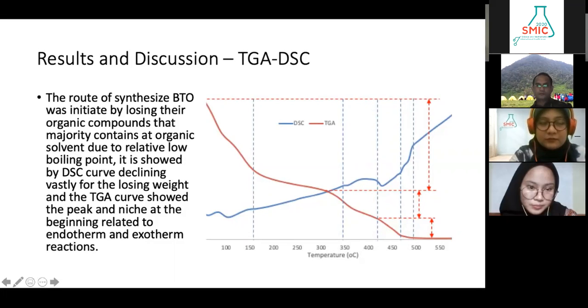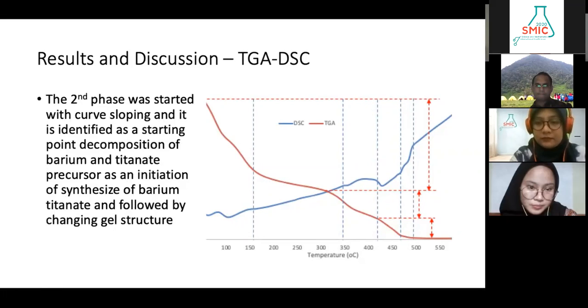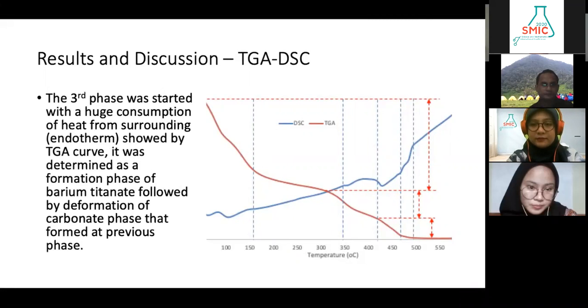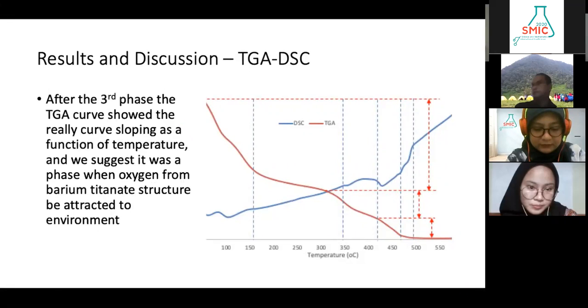Then the TGA showed a peak and knees at the beginning related to endothermic and exothermic reactions. Then the second phase started with a sloping curve, identified as the starting point of decomposition of the barium and titanate precursor as an initiation of synthesis of barium titanate, followed by a change in structure. Then the third phase started with a huge consumption of heat from the surroundings, shown by the TGA curve, and it was determined as the formation phase of barium titanate, followed by decomposition of the carbonate phase formed in the previous phase. After the third phase, we suggest it is a phase when oxygen from the barium titanate structure is attracted to the environment.